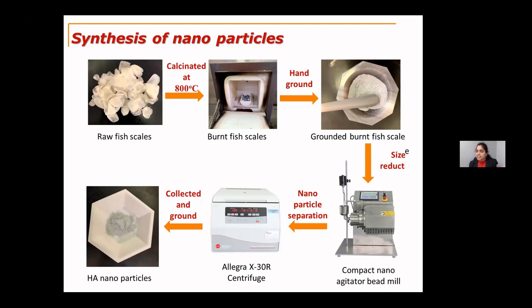This is because we did a rough thermogravimetric analysis on these fish scales. Raw fish scales contain a lot of collagen, carbon content, and then proteins, lipids, fats, and a lot of other materials. So we chose to do a rough thermogravimetric analysis, which shows the decomposition, and we figured out that around 700 to 750 degrees centigrade, the hydroxyapatite was left, and before that everything would be decomposed. So we chose to calcinate it around 800 degrees centigrade, for 3 hours.